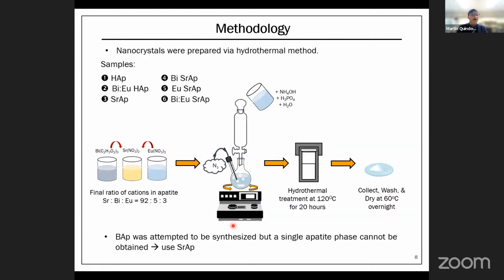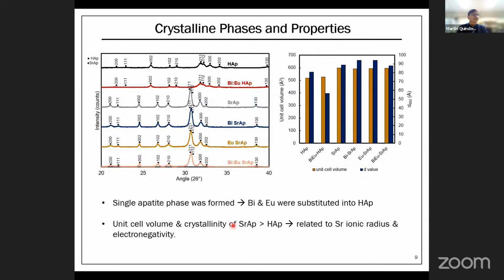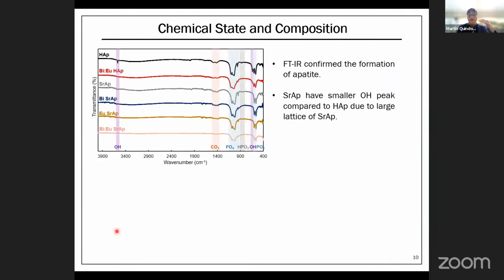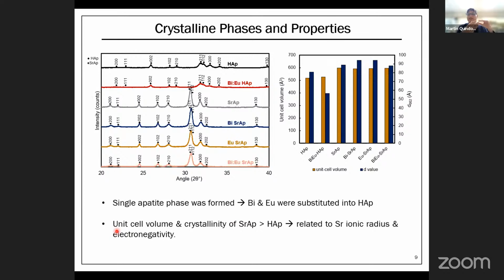However, if you check my XRD plot, the crystallinity is not so good. Because the crystallinity is not so good, we cannot make a good fit from the Rietveld analysis. So we cannot get very good atomic coordinates experimentally. That's why we ended up not comparing the atomic coordinates from the DFT and from the XRD.